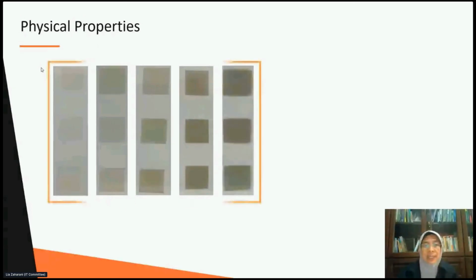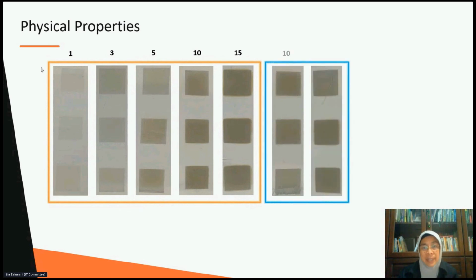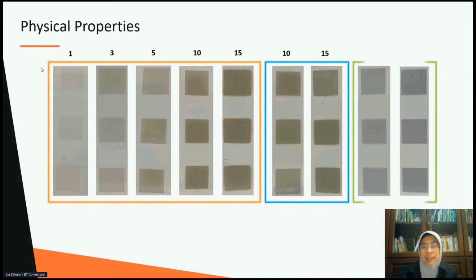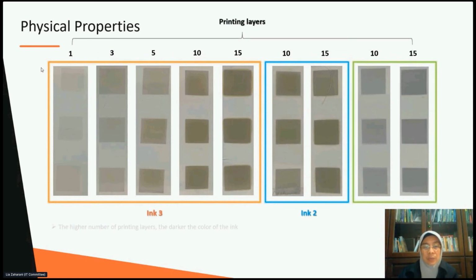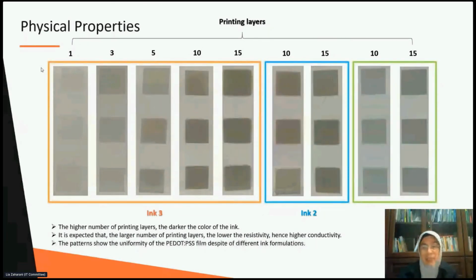So this is basically the physical properties of the inkjet printing onto the fabric materials. This is 1 layer, 3 layers, 5 layers, 10 layers, and 15 layers of printing. You might see that this is 10 to 15 layers with different materials. This is ink 3, ink 2, and this one, green in color, is ink 1. The higher the number of printing layers, the darker the color of the ink.